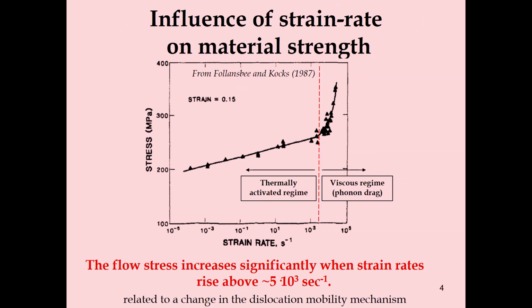And somewhere around 10 to the 3 to 10 to the 4 per second, we see a significant increase in the strain rate sensitivity. And this turn-up is of interest for many materials we're looking at, and especially how to get to this very high regime of strain rates. This threshold, or where we see the strong turn-up, is related to a change in dislocation mobility.